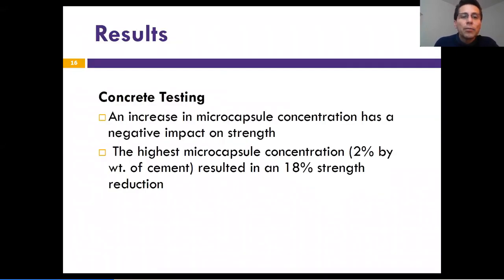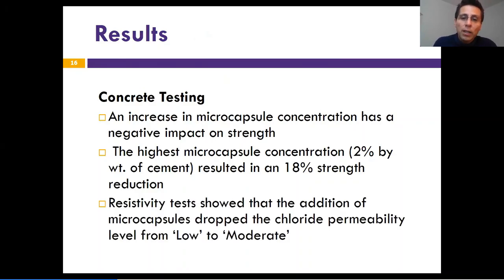So the results can be illustrated here. The concrete testing, in terms of physical properties of the concrete, shows that an increase in the microcapsule concentration has a negative impact on strength. That's something to consider in terms of the concrete properties. And the highest microcapsule concentration resulted in an 18% strength reduction, okay? That's again very important to consider.